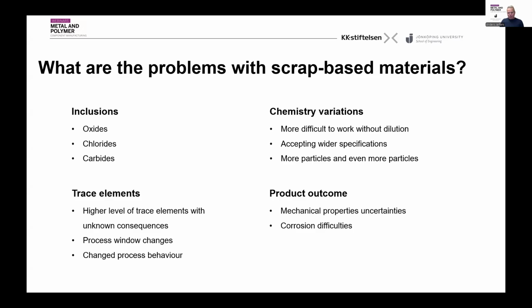Now, with the scrap chemistries, you have variations in chemistry. So there are ways that we normally do. So one part is to dilute the scrap. But this is very difficult. If you have a small variation of a trace element and you need to halve that, that means you need to have 50% dilution. So that is one element to deal with. Trace elements can make huge amounts of dilution necessary.